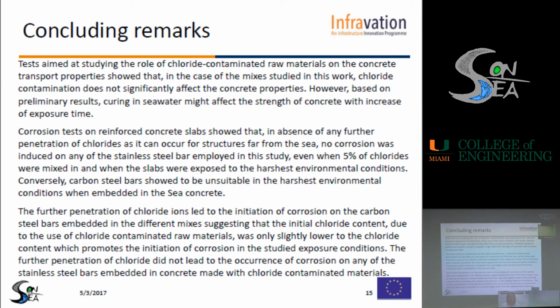Corrosion tests on reinforced concrete slabs showed that in absence of any further penetration of chlorides, which can occur for structures far from the sea, no corrosion was induced on any of the stainless steel bar employed in this study, even when 5% of chlorides were mixed in and when the slabs were exposed to the harshest environmental conditions. Conversely, carbon steel bars showed to be unsuitable in the harshest environmental condition when embedded in the Sea concrete.